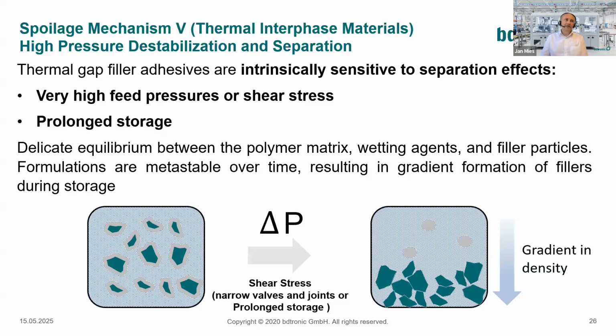And those materials form a sensitive equilibrium. That means over time, they have a tendency to form a gradient in the original container. That is one aspect, which we will see later in our results. The second aspect is that they have a tendency to de-aggregate, to separate under shear stress or high pressure feed in such systems. So this is also something we have to address when we want to process those materials in an industrial environment.